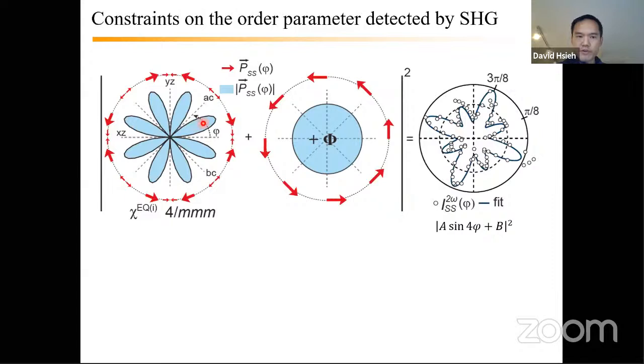in this pattern here. The optical phase is going plus, minus, plus, minus. We're measuring the intensity, so it's squared, so it looks to be of the same amplitude. But when you interfere that with another term, these phases then have constructive, destructive, alternating interferences, giving rise to this big, small pattern. And so the most simple way you can fit the data is just say, well, there's some isotropic term that turns on below T_N, somehow only in the S out channels. And that constructive interference then generates our data.